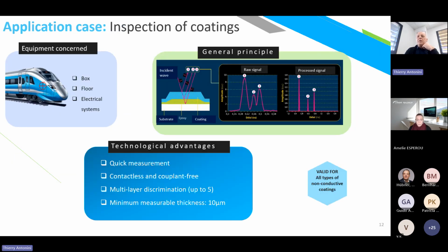I go now into detail on the 4 applications. So, inspection of coating based on time of flight measurement. Each interface gives an echo back to our system. And if we can measure the time between 2 echoes, you can have access to the thickness of the layer. The main advantage is that it is quite fast, contactless again and couplant free. Multi-layer discrimination is not the case of many NDT techniques, and the minimum measurable is down to 5-10 microns, and it can work whatever the substrate. It could be metal or a composite substrate.